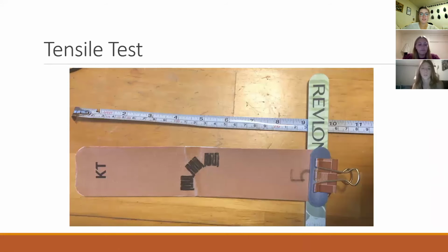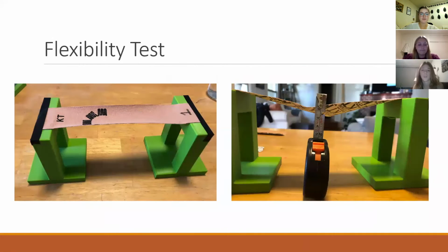Testing was performed to test our design against our engineering specifications. The first test was the tensile test, which verified that the sensors would have a consistent resistance after stretching to their maximum elongation. The tensile test showed that the tape did not sustain permanent deformation and was able to still consistently measure resistance post-testing. The next test was the flexibility test to ensure that the sensors can bend to their maximum bending angle and still function properly.